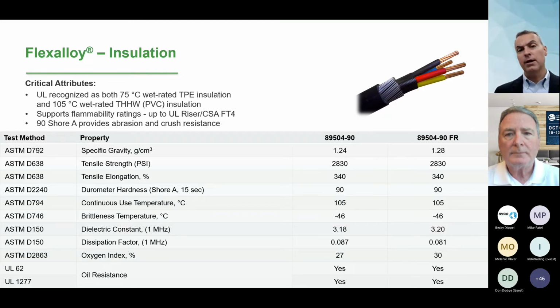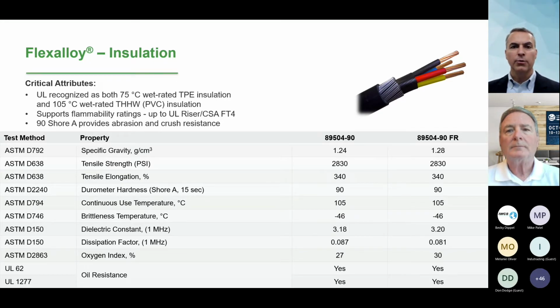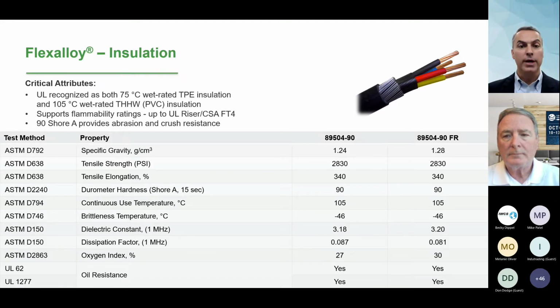We do offer an insulation grade with an 83 Shore hardness as well, which is also UL recognized. So, there are other options. This particular one we like because it has really good wet electrical properties. But just because it's 90 doesn't mean it's not going to be adequate for insulation. It is still very flexible depending upon the thickness that it's used at, but we do have a softer insulation available if that's what the customer would like.